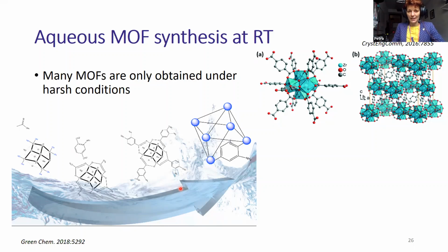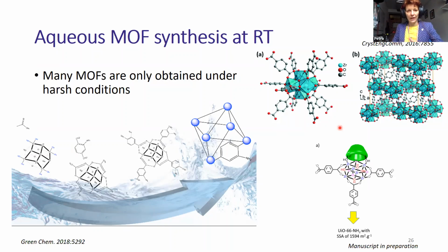However, you typically would synthesize it in DMF in harsh conditions. And what we found is what's very crucial for this framework to assemble is that in the precursor solution, we have to make this hexanuclear zirconium complex, which can form this inorganic node and then allow for the assembly of the framework. So since then, we looked at other modulators. So here we looked at acetic acid. We also managed to show that you can use starch or, well, starch-derived compounds for it. So again, maybe starch-based could be used.